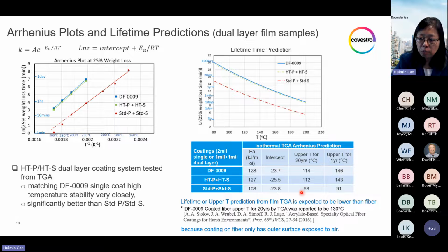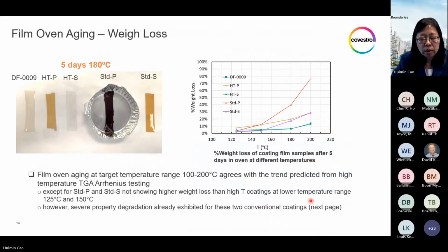So this gap is expected because in the fiber testing, the coating is only exposed to the air from the surface side, one side only. Instead of the film test, the bottom is just loosely sitting on the pan. So the sample, this very small sample, is exposed to air from all sides, top and bottom, left and right. So the film test is a much more severe test than the fiber. So once again, all these predictions are only for relative ranking purposes.